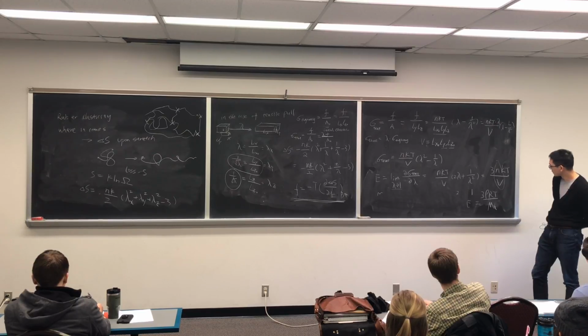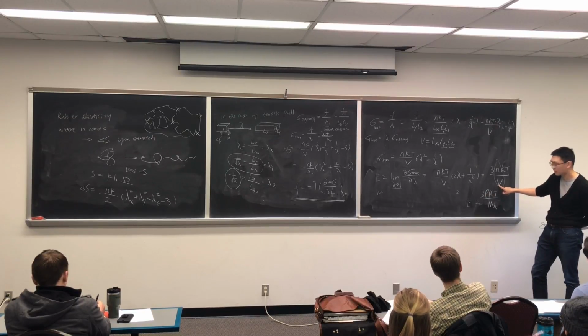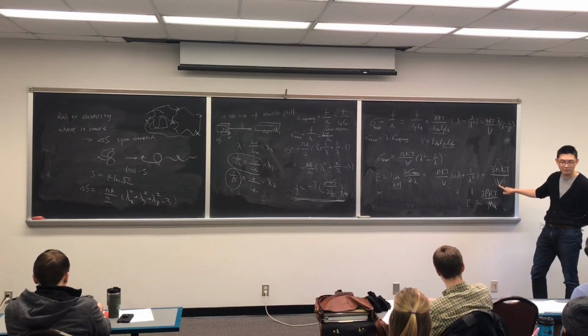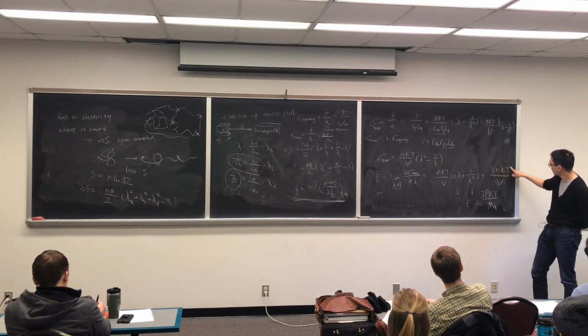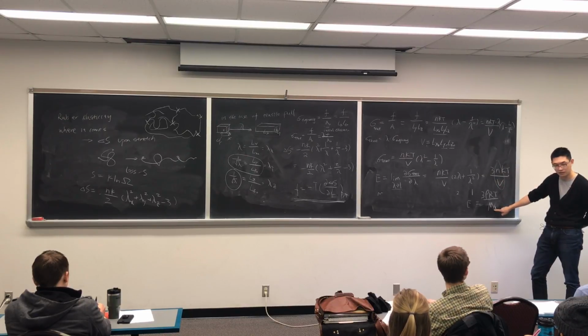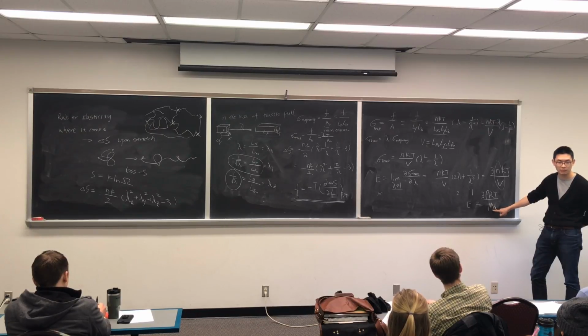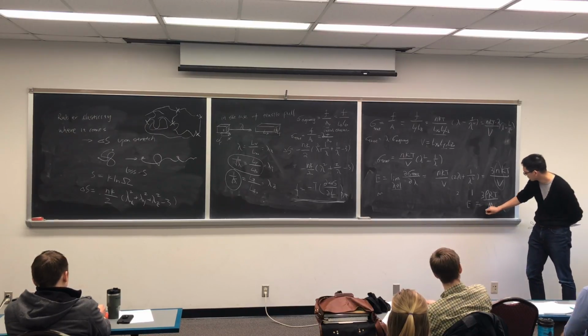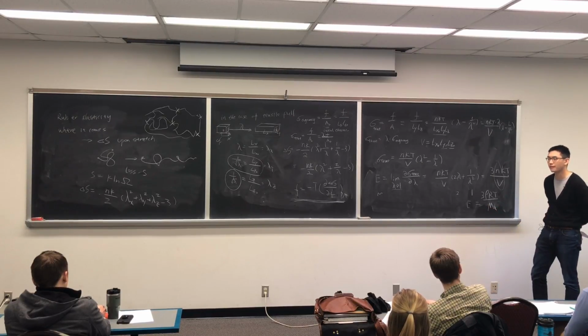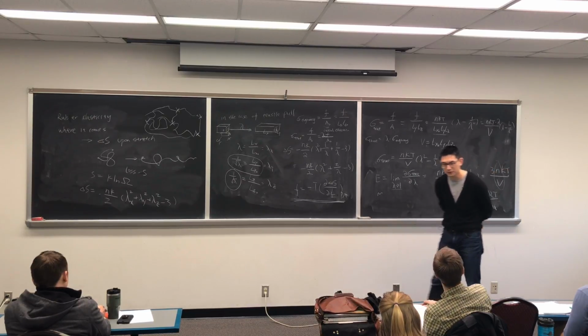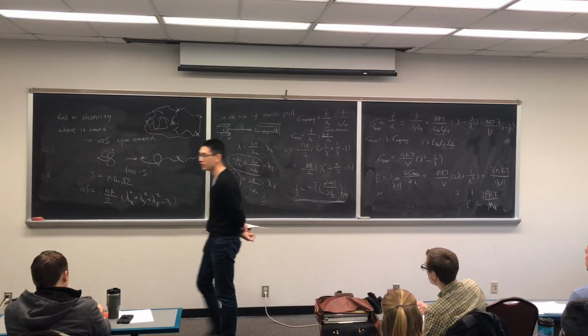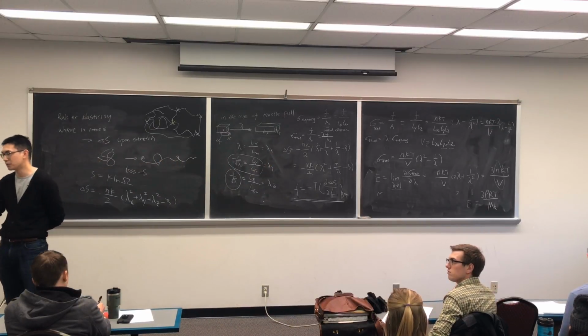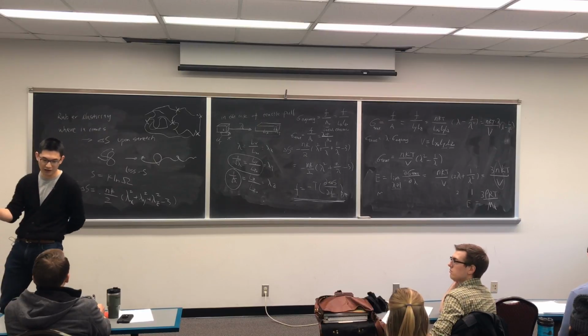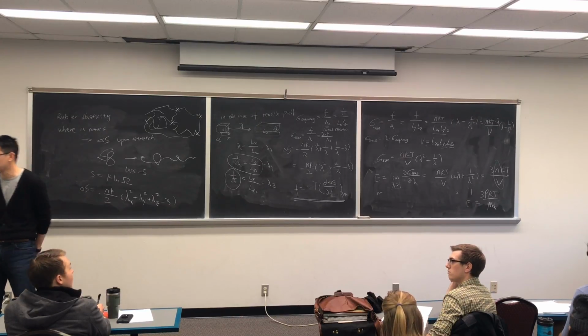How do we rationalize this? Density multiplied by volume is how much material you have. If you use the top, n multiplied by the molecular weight between the points, that's also the total amount of your material. So you can use this relationship to understand your system. In other words, if you know how big your material is, and you know the cross-link density per volume, you can calculate how many crosslink points you have, and you can get the molecular weight between the crosslink points.